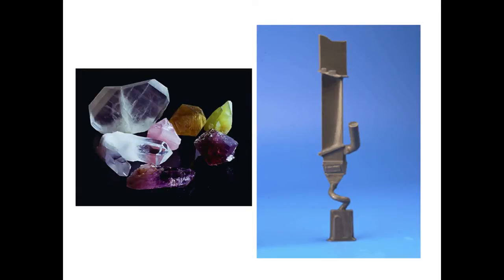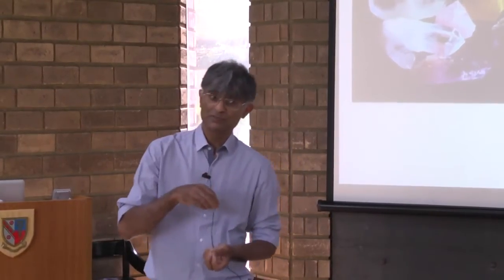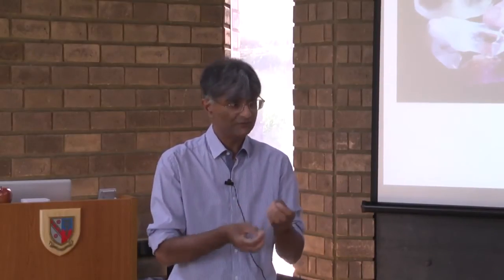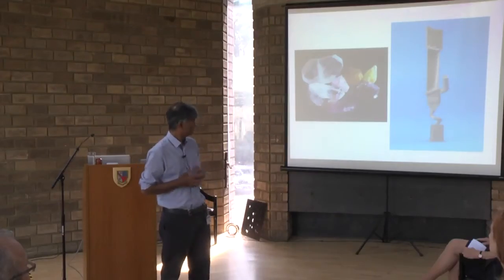So here, for example, is a single crystal, which is a turbine blade that goes into an aircraft engine. There are thousands of these grown by Rolls-Royce annually to put in aircraft engines, because if we have boundaries between crystals, there are defects, and atoms can diffuse rapidly between those boundaries. And these things serve at temperatures of about 1400 degrees C, rotating very, very fast. So they get longer if diffusion happens. So if you make them as single crystals, then they are very strong at high temperatures.